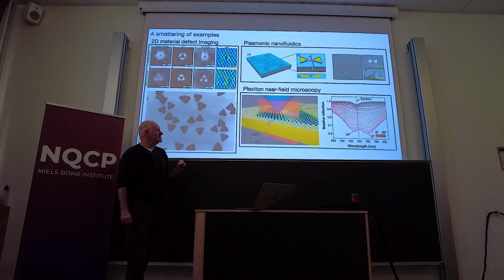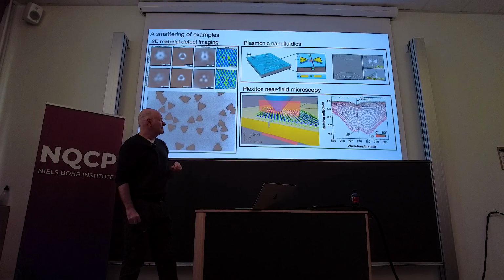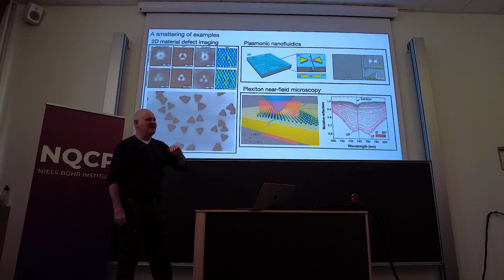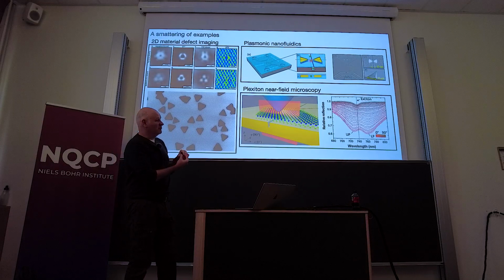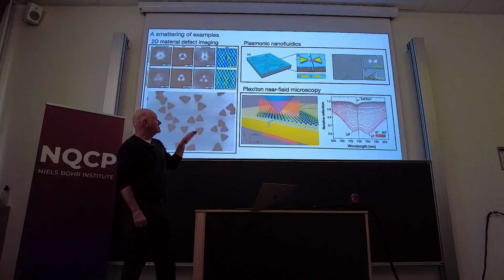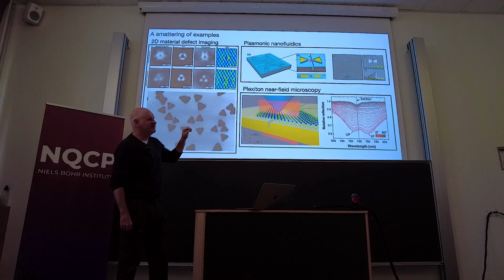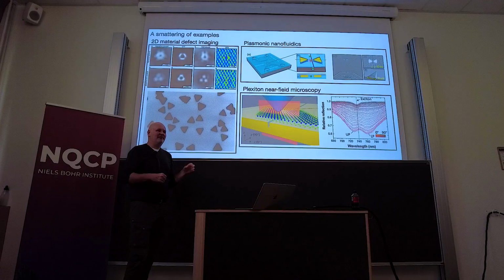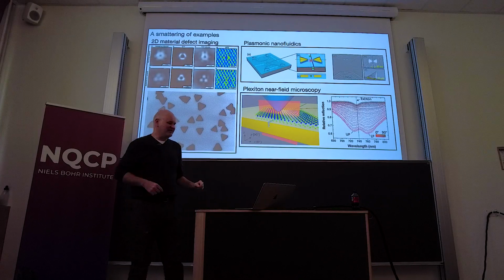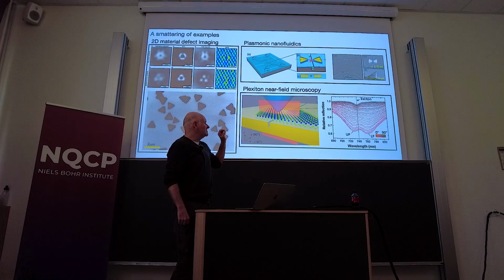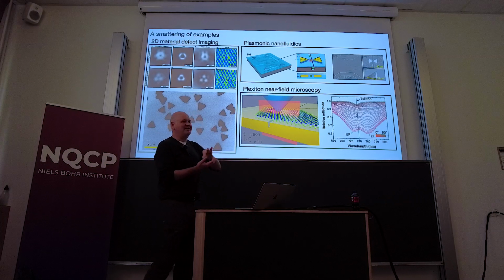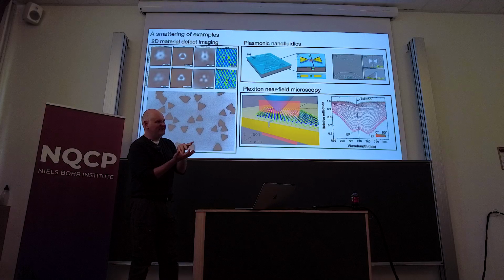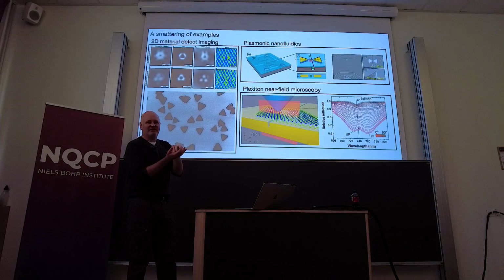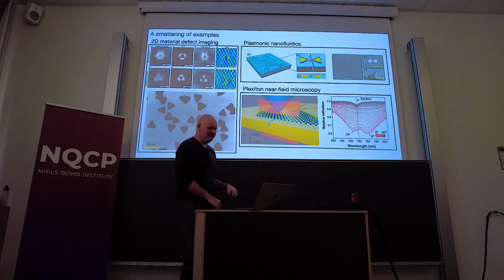And then lastly, this is a more recent one, more 2D materials, where we put TMDs on top of nanofabricated plasmonic grooves essentially, and are actually able to measure plexitons in near field. A plexiton is a coupling of a plasmon and an exciton. It's an exotic particle. People like exotic particles these days. And you can measure these and modify them by pressing the AFM tip into that groove, causing strain and forcing it into the groove. So all kinds of cool stuff.